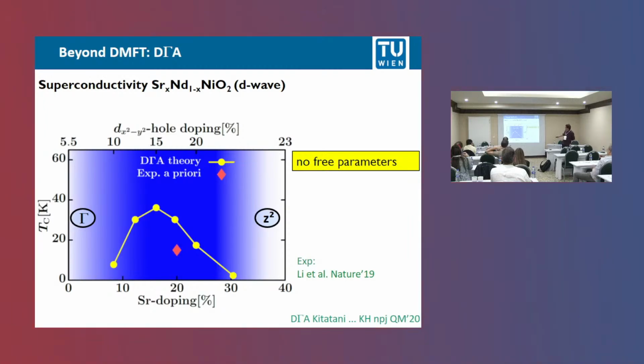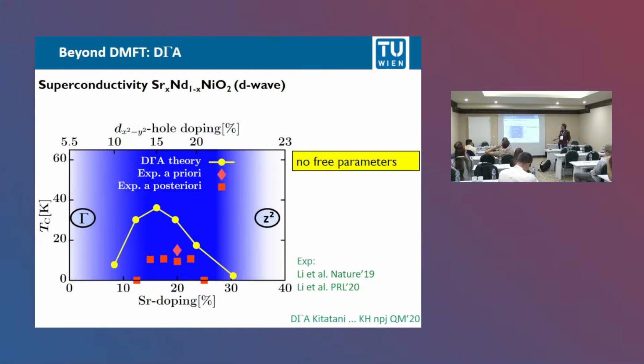And that is the calculated Tc at a time when there were only one or two data points at 20% doping available. So this data point. There are no free parameters, and the agreement for such a difficult to calculate quantity as a superconducting Tc is quite good. And then further experiments came, first in 2020, also by Ariando, but I put here all the data from the same group in Stanford, and you see a superconducting dome.